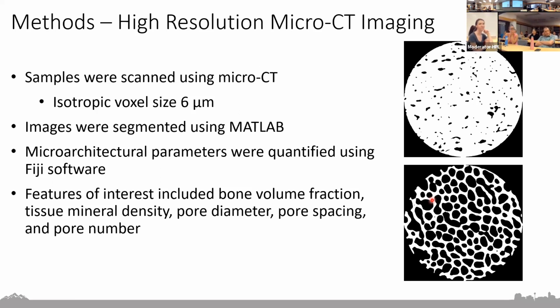So you change it based on the specimen, rather than a constant modulus. Yes, because the apparent modulus, which you get from the mechanical test, is largely determined by the effective cross-section area of the bone, the microarchitecture, and the tissue elements. Essentially, it's a linear elastic finite element analysis. We do the analysis, we get the apparent modulus of the sample, and we compare it to the apparent modulus from the experimental test. That tells us how we should change the tissue modulus in the finite element model so that they match.